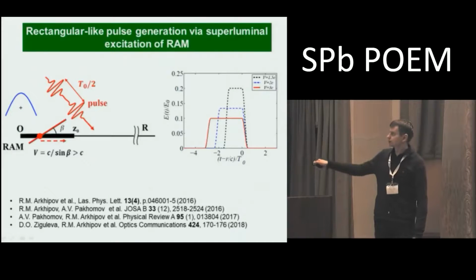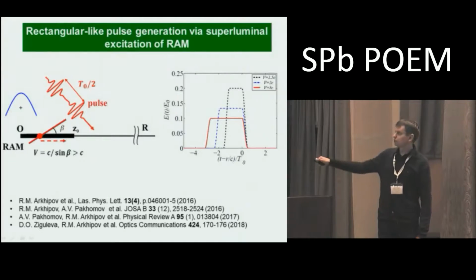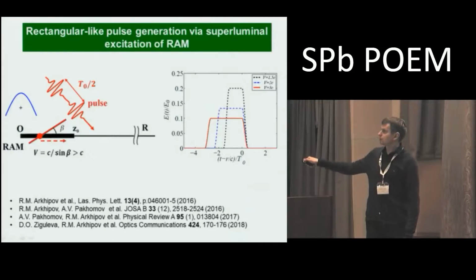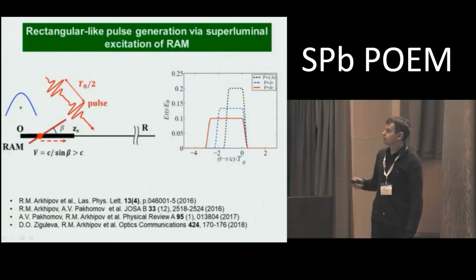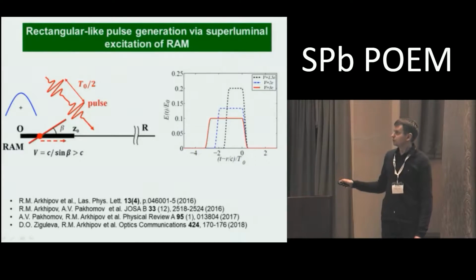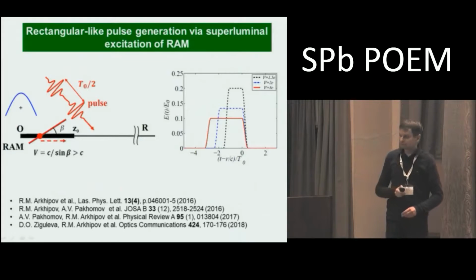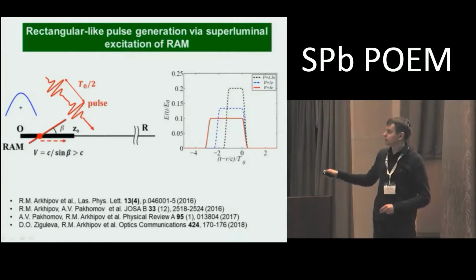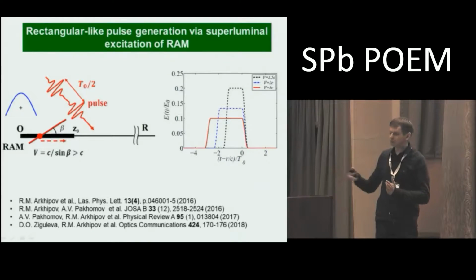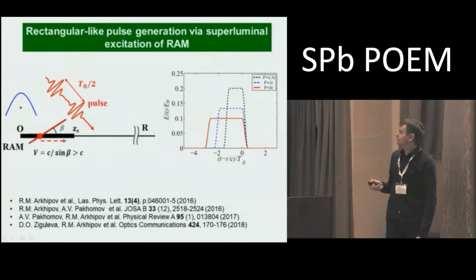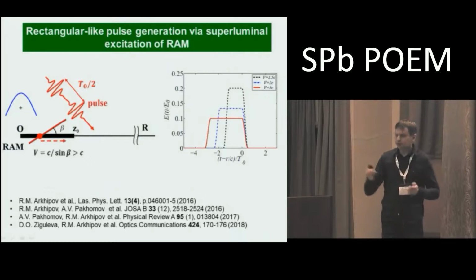So under such conditions, the medium is excited at superluminal velocity because the wave front is limited at some angle, beta, to the medium. And the excitation cross-section point moves along the medium at the velocity which is faster than the velocity of light. So each point of the medium illuminates such a half wave, and since the excitation velocity is faster than light, at the far field zone, these half waves come with some delay to each other. And this allows us to generate pulses with exotic rectangular-like wave shape.